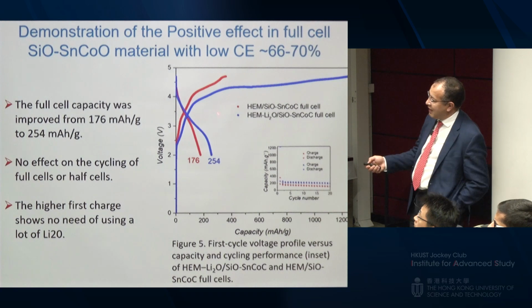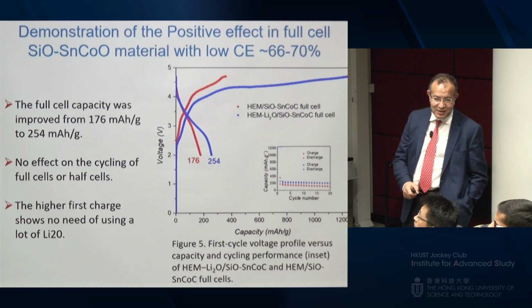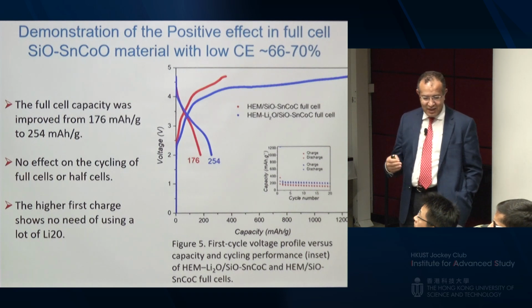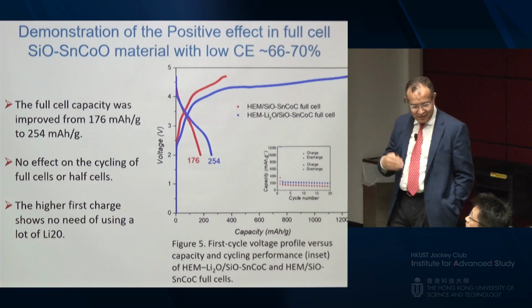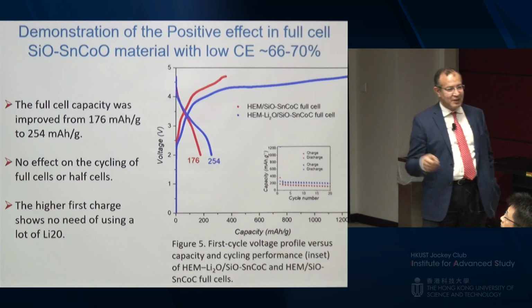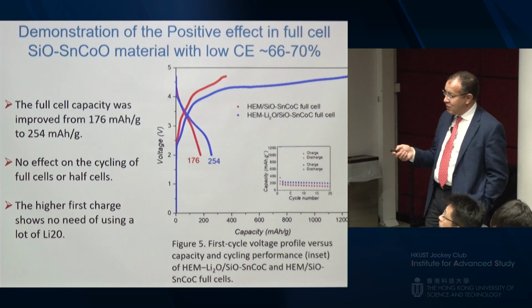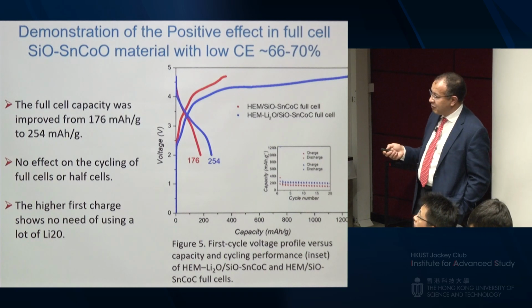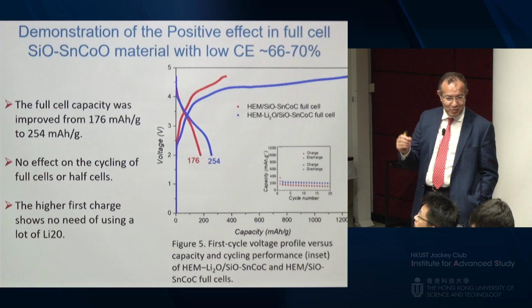irreversible loss. We add 1% lithium, and you can see we recover all the capacity of the cathode because the lithium was able to provide the lithium to the silicon, and then now you can cycle the capacity of the cathode easily. So this one also has been licensed because it's very simple. It's cheap, just 1% of material that is commercially available.